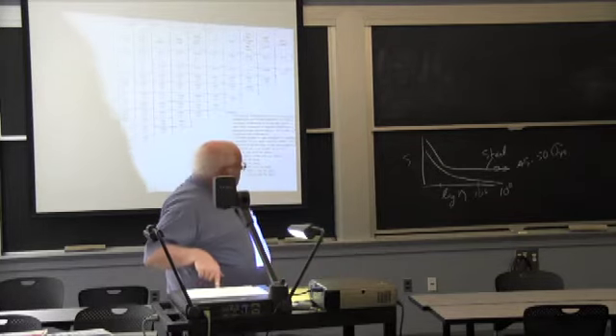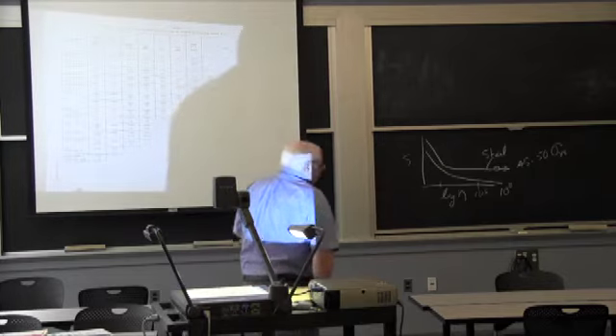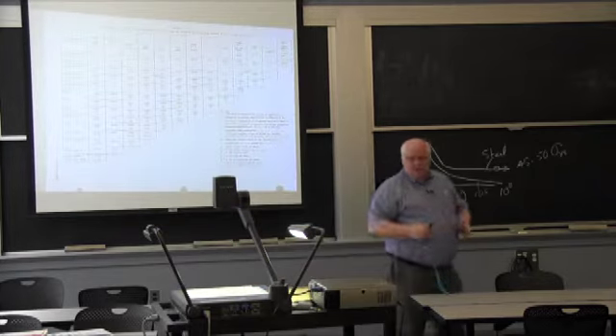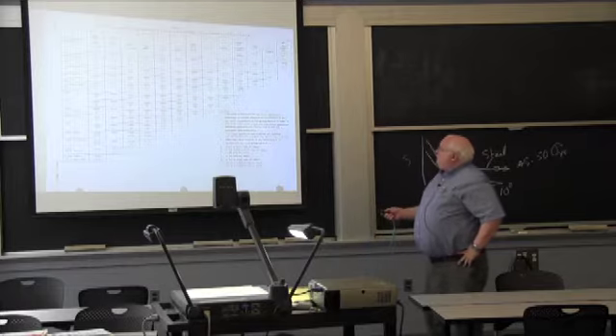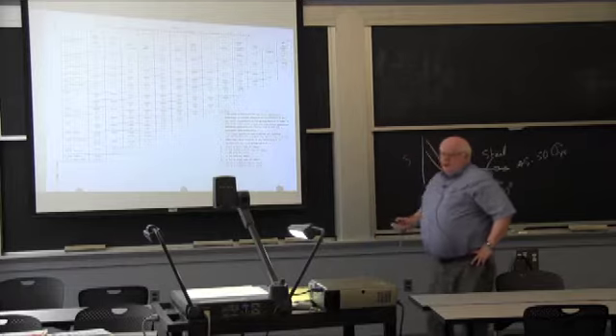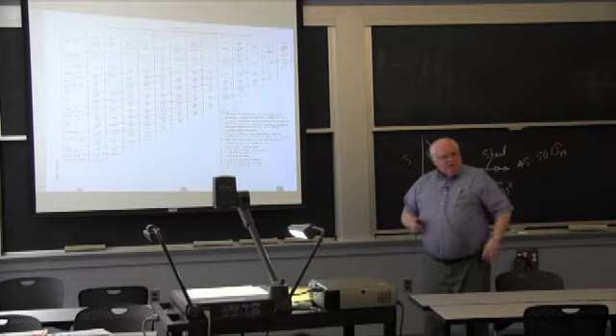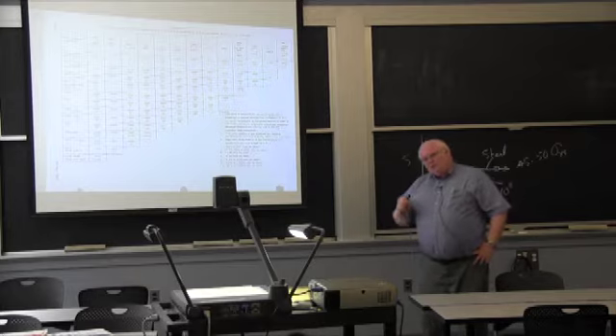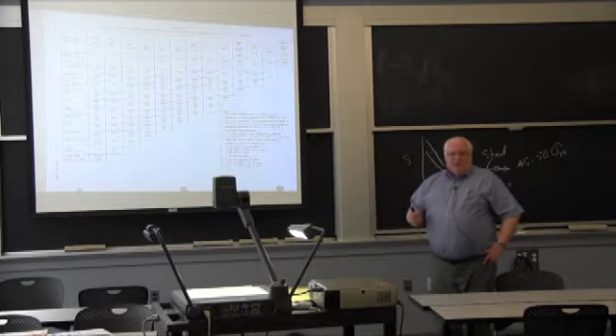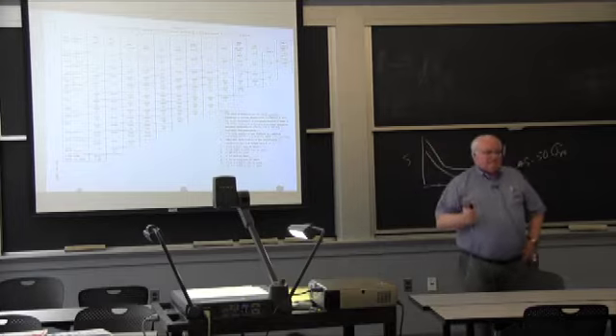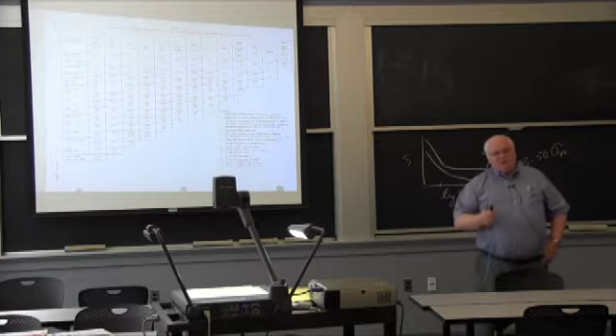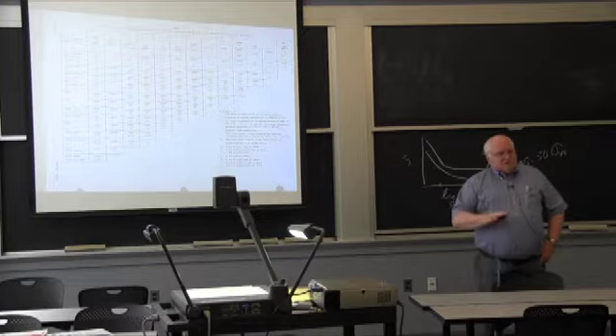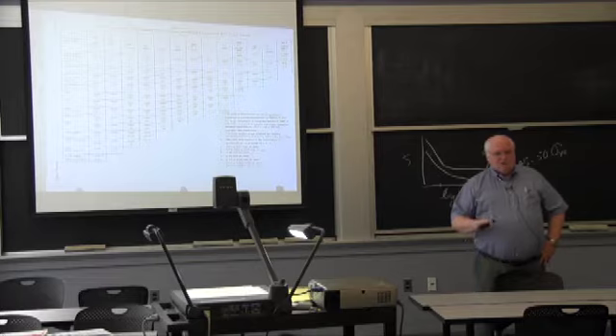But most of the weldable aluminum alloys that can develop full strength in the weld, there's a host of alloys with a number of different filler metals. You can't just use any old filler metal with aluminum. If you use the wrong filler metal with the wrong alloy, then it's going to crack, and you can't prevent it. There are some aluminum alloys that just cannot be welded without cracking. A lot of the 2000 series that they rivet aircraft out of, they rivet them because they can't weld them. If you try to do fusion welding on a 2024 aluminum, you just have cracks in the heat affected zone.